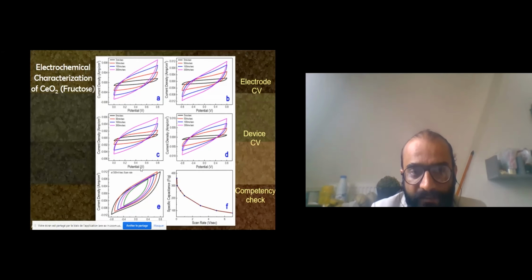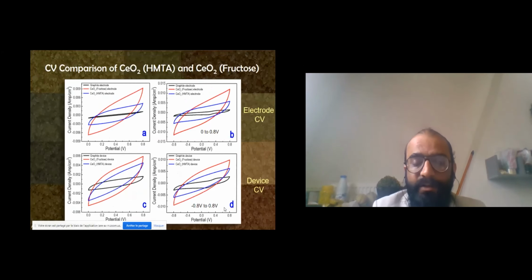Similarly we have done it for fructose. Because of the amorphous nature, it must have some more porosity effect, and we have seen up to 350 farad per gram. The specific capacitance from charge discharge and from CV is both very high. If you do the comparison, you can find the fructose based material is more efficient. This is electrode CV and device CV.